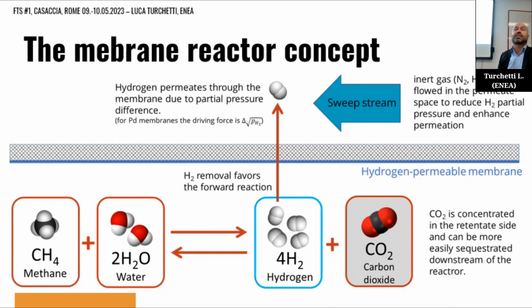And another advantage is that your product hydrogen is here. You have also very pure hydrogen here because these membranes are very selective. And your retentate, which means what remains upstream of the membrane, is also a concentrated CO2 stream and water, and depending on the extent of the reaction and permeation, can contain some residual methane and hydrogen, but it's very concentrated in CO2, which also means that if you want to capture this CO2, this is facilitated. So you have several advantages.